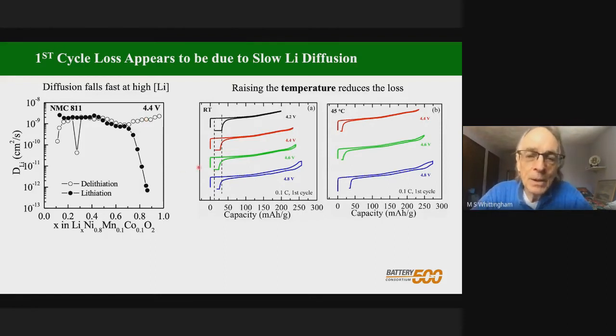So let's look at how we also tested that this was really a function of the diffusion coefficient. I show you here 4 plots to different charging voltages, 4.2, 4.4, 4.6, 4.8. As expected, we get more capacity the higher charging we go to. But you can also see by the time we got to 4.8, the charging and discharging curves are separated, which means we're getting some polarization, and this is due to decomposition of the electrolyte. What I want to show you here is if we discharge at 2.8 volts, then hold at 2.8 volts, we can get more of the lithium in. This is this one, same here, same on the green one.